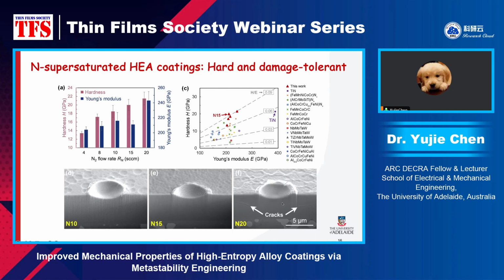But from the cross-sectional SEM image, we cut the indents using the FIB. We can see that the sample with the highest nitrogen, the N20, shows some lateral crack. It's not very clear here, but indicated by the arrows. While the others showed no crack, and at the same time, they showed large deformability.